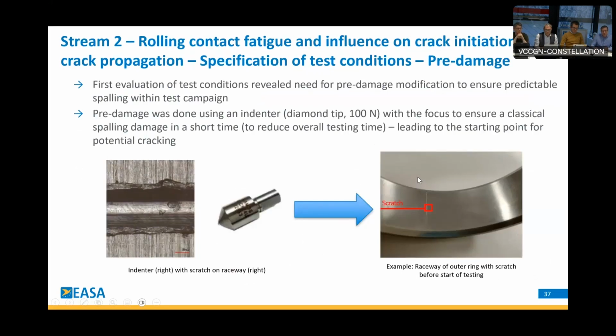Before we did the live testing, we had some test specimens and we used some standard indents, which are comparable to some overrolling, some indents which you could expect. But we saw that the initial damage, the spalling that we need, took so long that it would not be feasible in the time frame of this project to wait for this spalling, which is also a little bit not predictable. Therefore, it was selected to have a pre-damage modification to ensure a plannable and reproducible spalling damage.